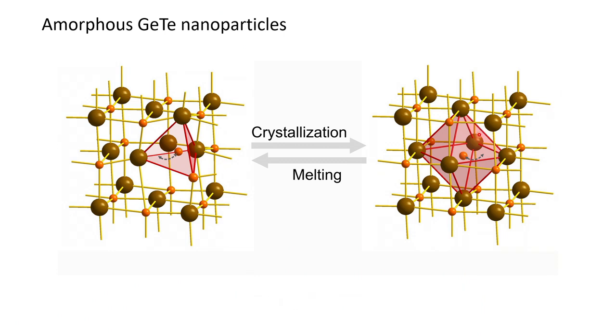You see the octahedron around the germanium atom, and now when you move it just enough to become a tetrahedral arrangement, then you get the tetrahedron here. And this movement of the atom, a 2 angstrom movement, should be fast. Of course, it also triggers a little bit of reconstruction of the other two atoms around this, but essentially, in a nutshell, it's a movement of a single atom. This is very encouraging for us. Why? Because we see the perspective that we can scale down our memory cells to a single atom. So this will be a single atom memory, ultimately.